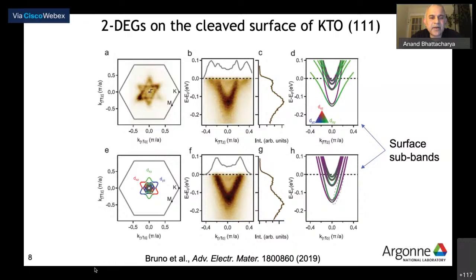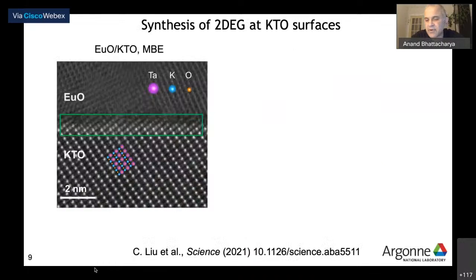All right. So fine. I should mention though that experimentally, at least, there's no direct evidence in the photoemission yet, as far as I know, for this sort of spin splitting or Rashba type thing. It's theoretically predicted to be there, but they haven't seen that very clearly in the 111 2-degs yet. So, okay, our samples.